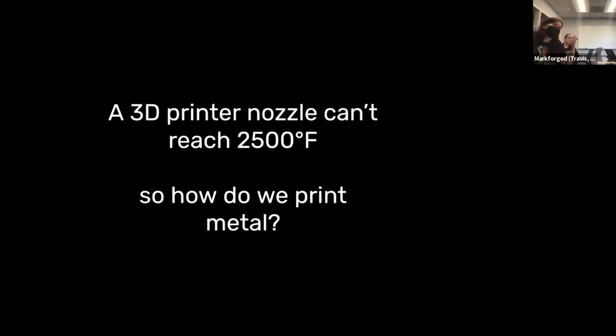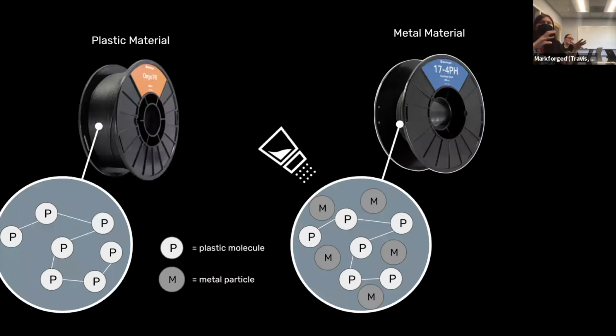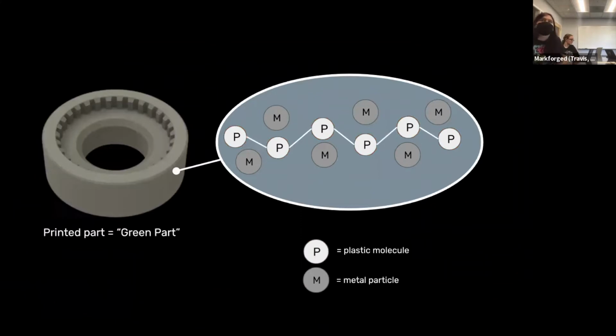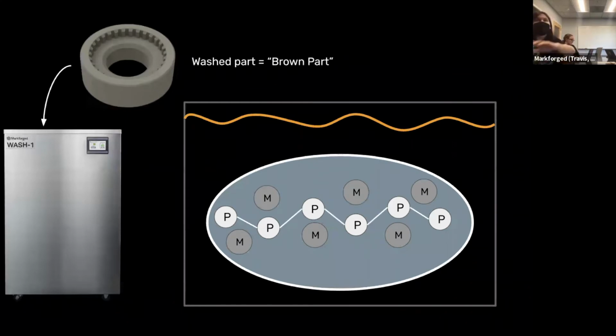The way that we approach it is by adding a plastic material into the mix of our metal filaments. And then when we are actually printing, by heating to the melting temperature of the plastic, the material is still able to flow through the nozzle with the metal particles just going along with it, instead of the metal itself having to be melted. Following that step, you have what's called the green part, which is what you take off of the printer system itself. And that then goes into the wash, which is a different stage of the metal process. After the wash, you have a brown part, and most of the plastic has been washed out by the special solution in the wash.